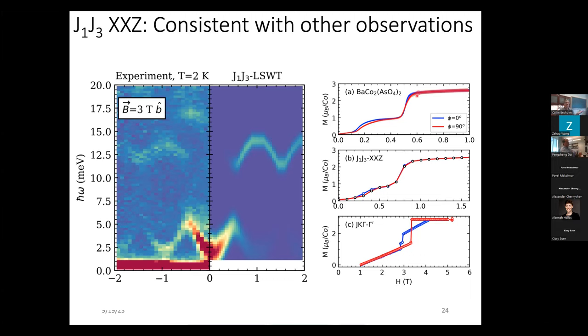This saturation is actually not strongly dependent on the orientation. That is exactly what you get for the J1, J3, XXZ model that we postulated. It does give this kind of almost isotropic in-plane behavior. Whereas whenever you have a dominant Kitaev interaction, then it becomes extremely anisotropic in its magnetization response. And so we're mentioning this because that can be a fingerprint of Kitaev physics, a fairly anisotropic in-plane magnetization curve. This is not seen in this compound.